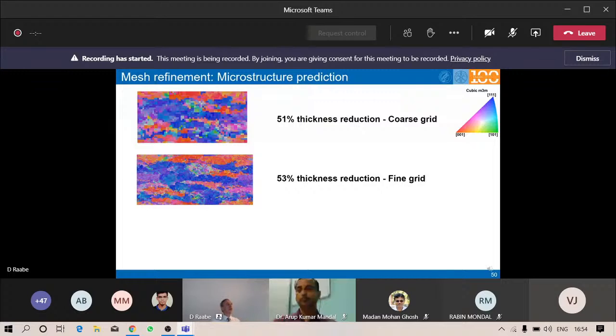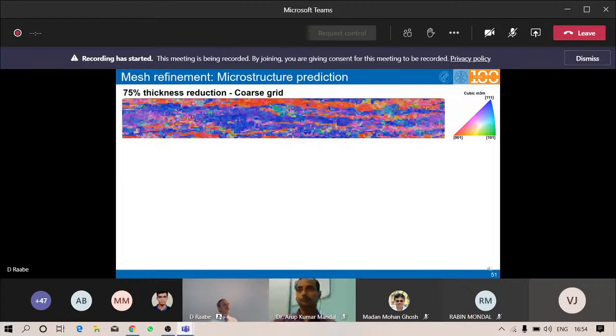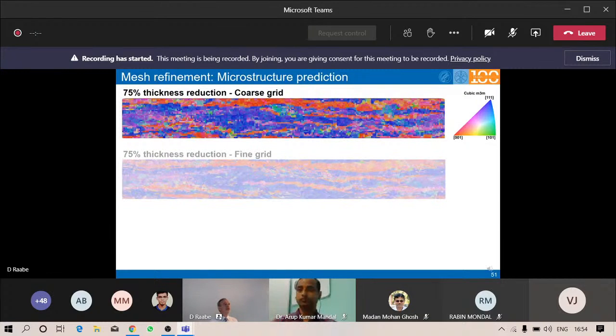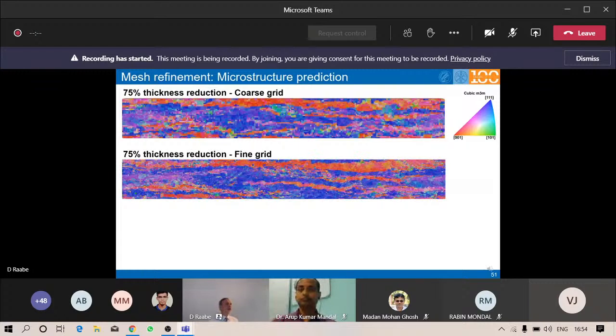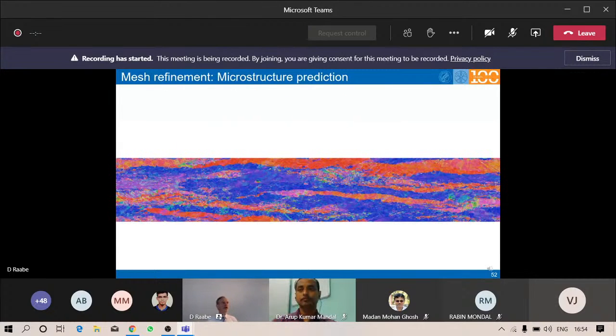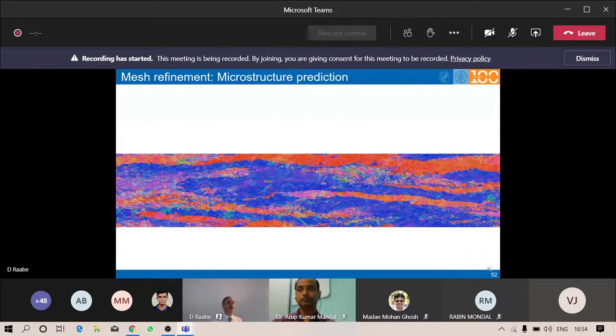And you see when you go now to higher deformations and go from that coarse grid to a very fine mesh, you see what level of detail you are capable of obtaining nowadays with such crystal plasticity calculations. When you just look at the bottom image, 75% thickness reduced IF steel, so it's relatively close to pure iron, then you see a quality of the calculation. This is a spectral calculation, a fast Fourier solver with DAMASK, where you see a microstructure that looks very similar to what you typically know from EBSD and microscopy measurements.